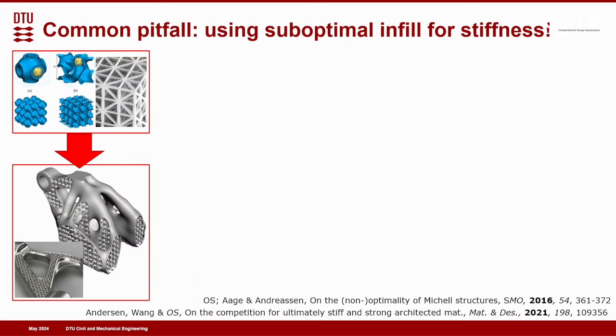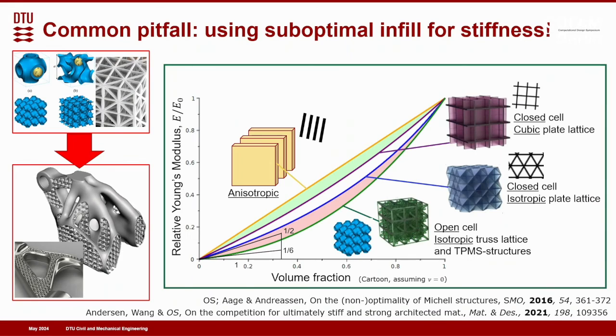But sometimes it's quite dangerous to take an already optimized design and then just substitute microstructure into it without doing additional verifications and optimizations. And why is that? Well, we can take a look. Sorry for this graph, it's a little bit busy, but it shows us the Young's modulus as a function of the relative density of our composite. Ideally, to motivate microstructure, we want as high stiffness as possible for a given density. And we can achieve that with an anisotropic structure like the yellow one I'm indicating.